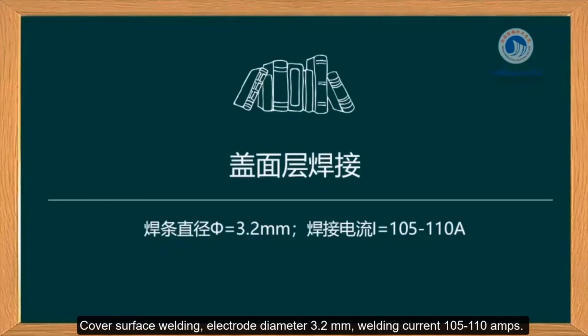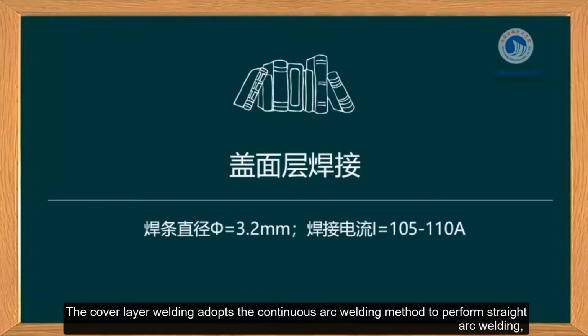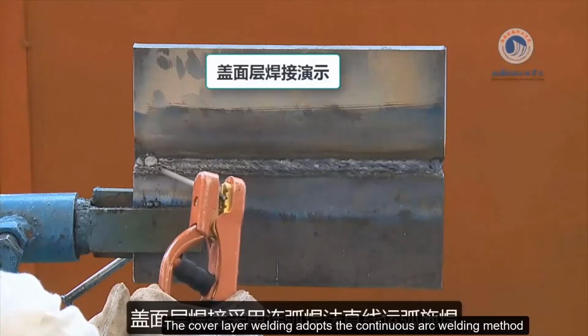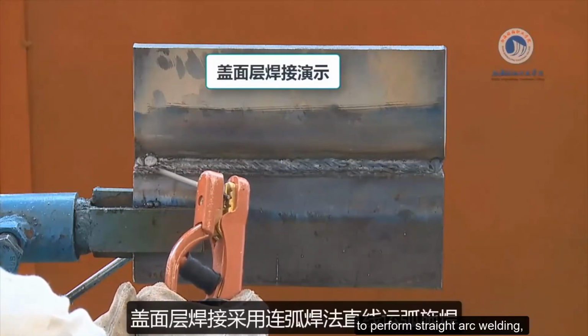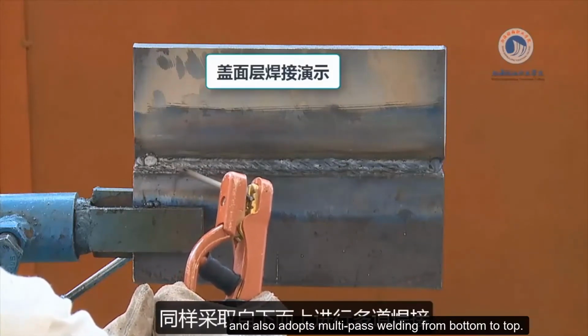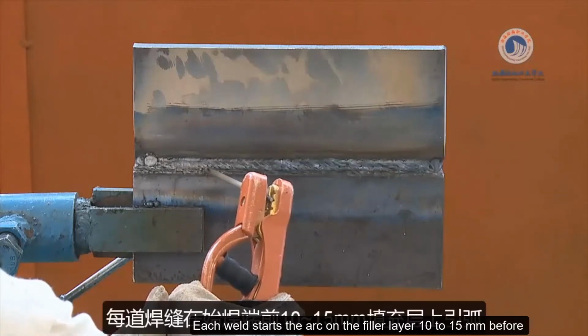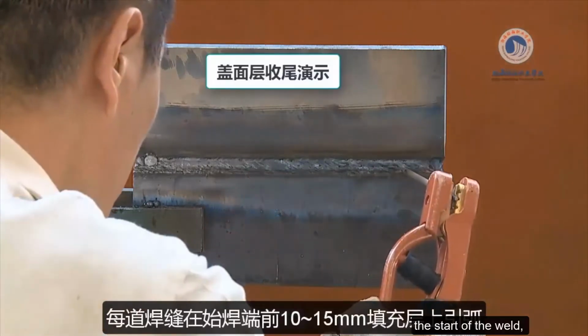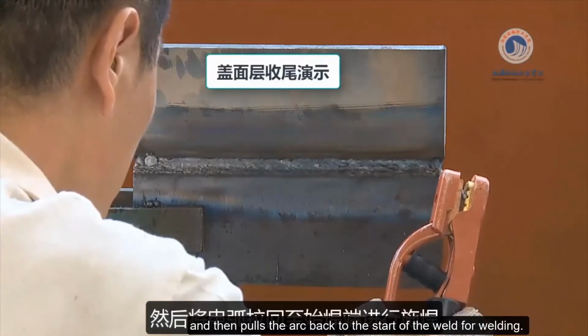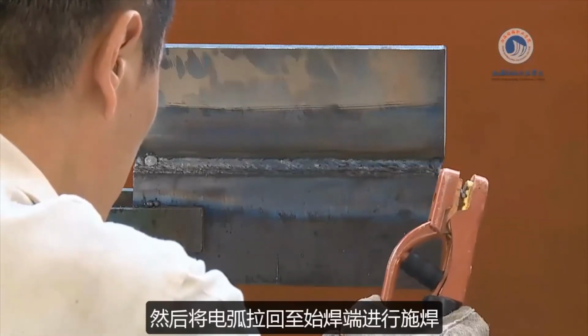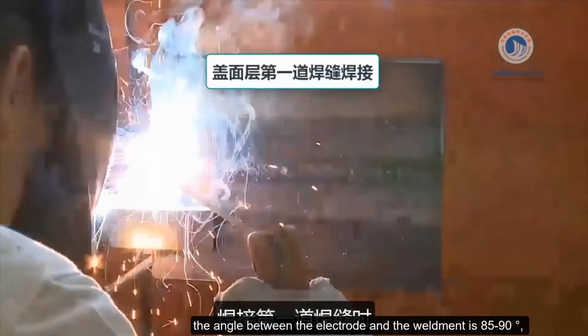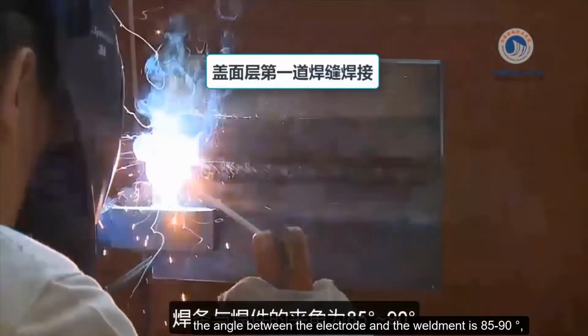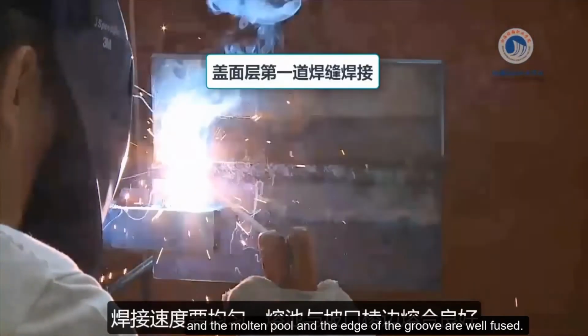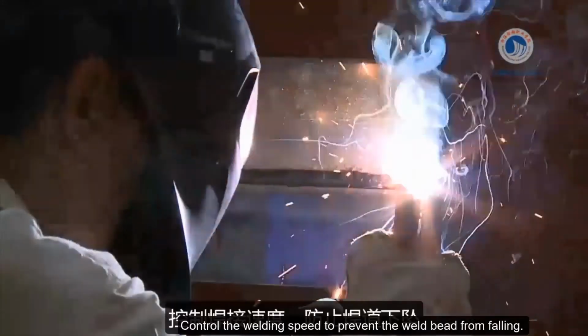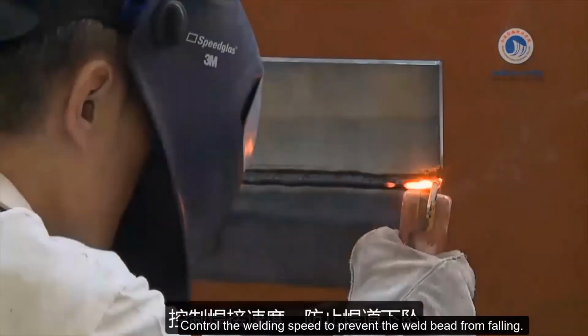Cover surface welding. Electrode diameter 3.2 millimeters. Welding current 105 to 110 amps. The cover layer welding adopts the continuous arc welding method to perform straight arc welding, and also adopts multi-pass welding from bottom to top. Each weld starts the arc on the filler layer 10 to 15 millimeters before the start of the weld, and then pulls the arc back to the start of the weld for welding. When welding the first weld, the angle between the electrode and the weldment is 85 to 90 degrees. The welding speed should be uniform, and the molten pool and the edge of the groove are well fused. Control the welding speed to prevent the weld bead from falling.